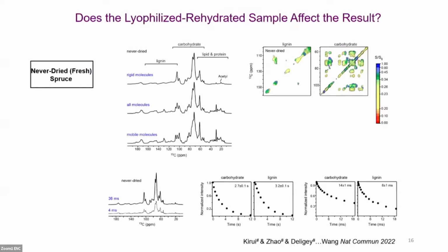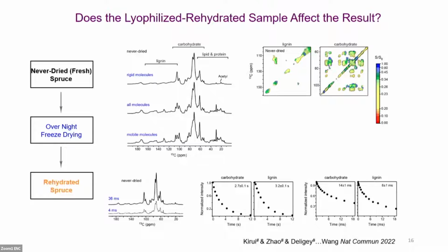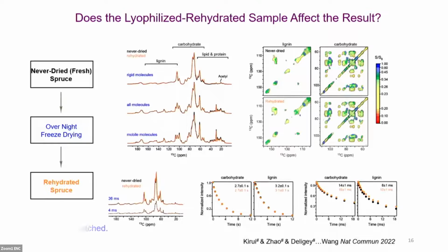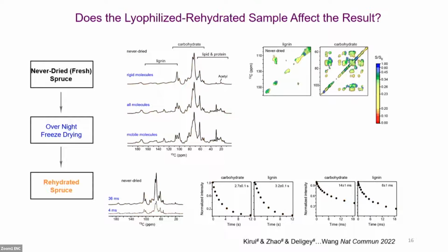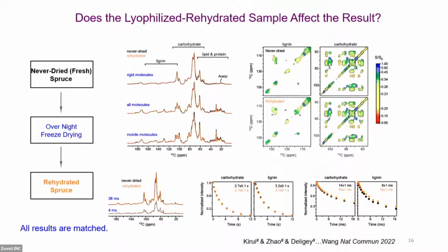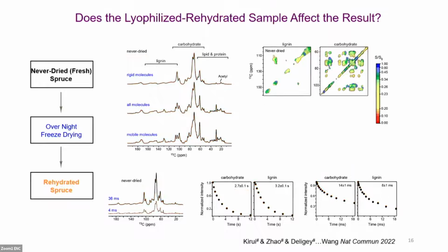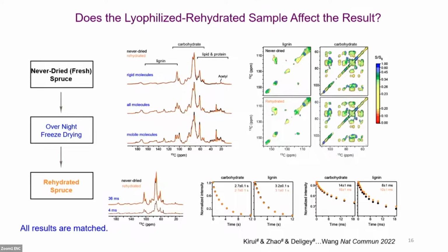Then we ordered a new batch of spruce samples. It's a fresh one, never dried. We collected the major 1D and 2D experiments and got this data. We did the freeze drying overnight by ourselves, rehydrated them, and collected all these experiments again with the same parameters. And then we can see the results matched well. That means the answer to this question is no, it doesn't affect it so much.